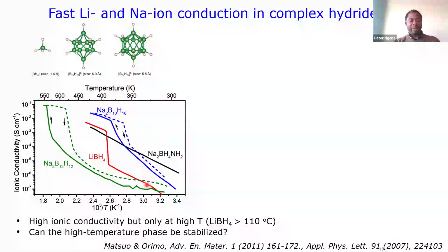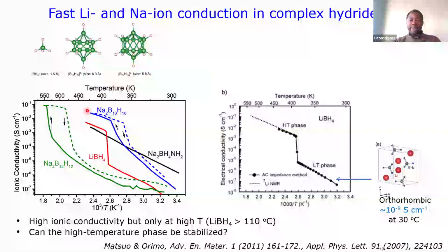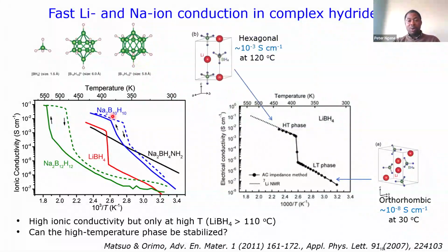What you see here, for example, if you pick this material, you do see that at room temperature, the conductivity is very, very low. And as soon as we begin to heat it to around 110 degrees centigrade or close to 400 Kelvin, you do see that it undergoes a phase transition, and then the conductivity is higher than 10 raised to the power minus 3 Siemens per centimeter, which is what is required for a battery. Which means that at high temperature, all these materials have very impressive conductivity. And so I just try to show it more here.